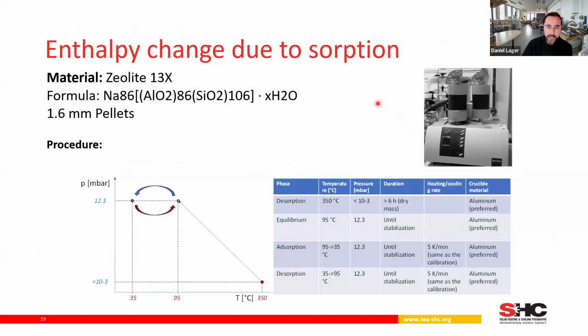For sorption enthalpy, we looked at a gravimetric system. Here we defined a standardized procedure where we desorb the material at 350 degrees C. It was again a zeolite 13X. And then we just measured the equilibrium at 95 degrees centigrade at a defined water vapor pressure.